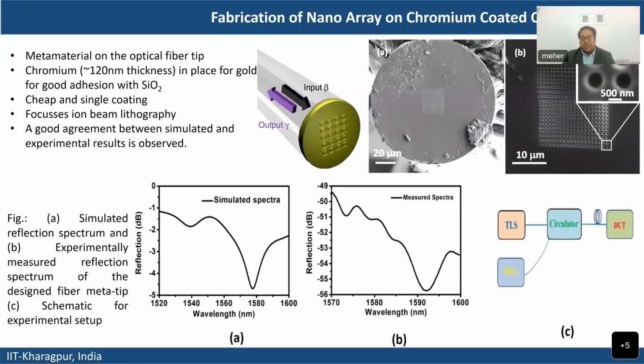So what we did, this is the tip of the optical fiber. If we cut the optical fiber cross-sectionally, you can see here that we made the patterns at the core. This is basically a single mode optical fiber. The core is around 8 microns. So covering the whole core, we made the pattern in around a 20 micron by 20 micron area, and these are just nano holes.